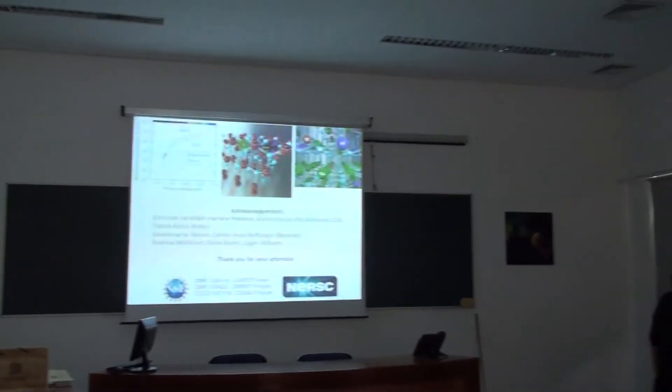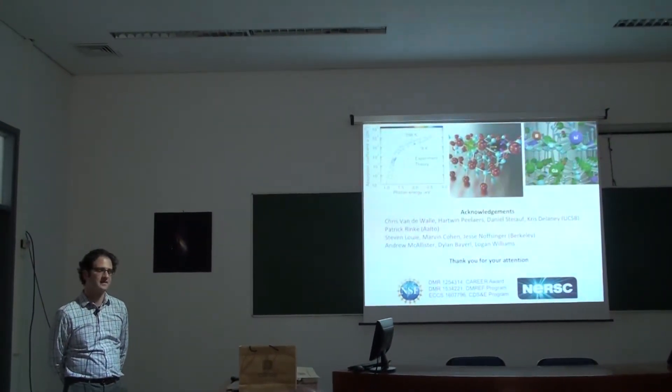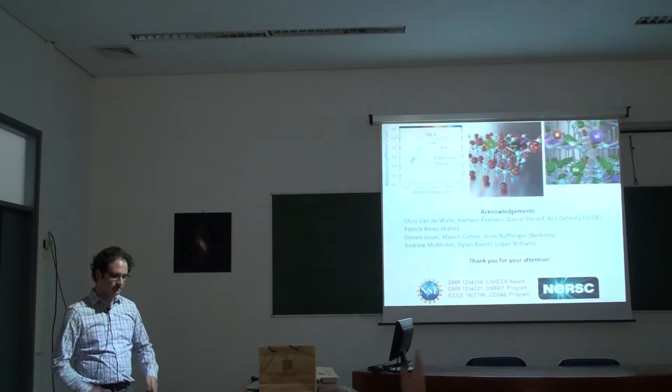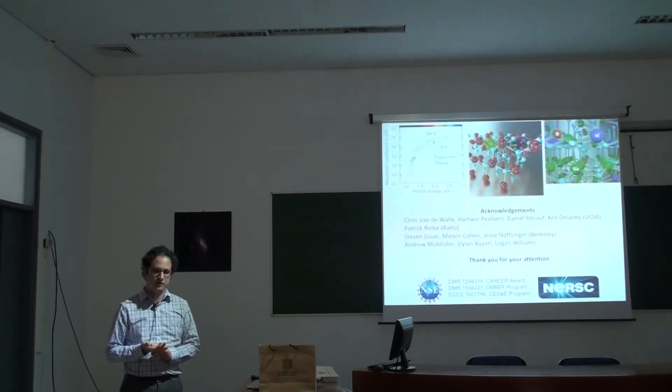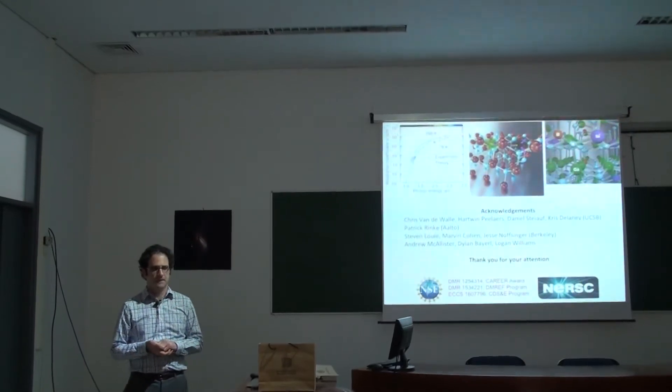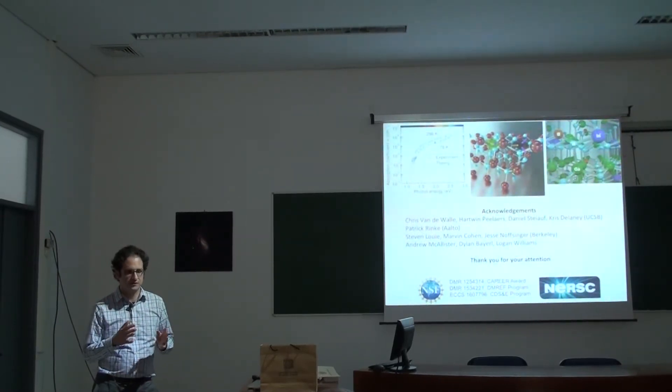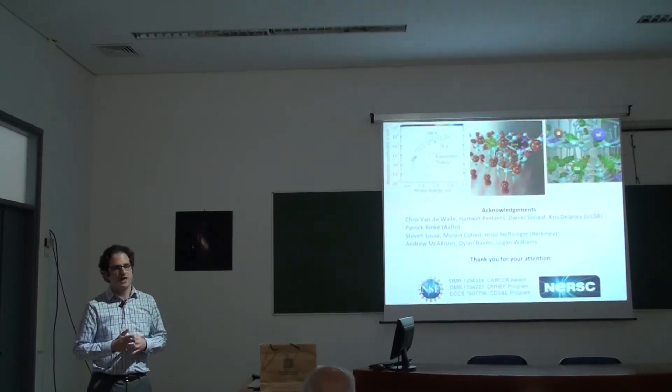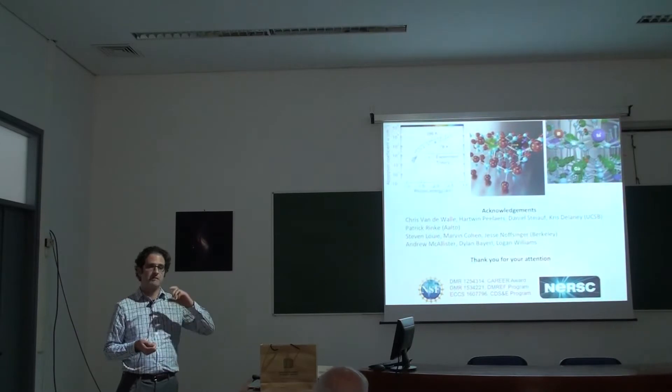Thank you very much. If you have questions? What is the form of the exchange-correlation functional you use, or is it different for different cases? Very good question. The question is about the exchange-correlation functional. I forgot to mention that in most cases we use the local density approximation, which is good for solids. Another one is the approximation by Perdew-Burke-Ernzerhof. They're equally good or equally bad for structural properties - they both give you about 1% difference in lattice constants. LDA underestimates, PBE overestimates. For solids it doesn't matter as much; for chemistry it matters a lot more to use more corrected functionals. The more important correction we make is to correct the band gaps with the GW method, because both functionals tend to underestimate band gaps. Sometimes we use hybrids - we use hybrid functionals that mix in some of the exact exchange, like hybrid functionals mixing some of the Hartree-Fock exact exchange. In that case if you use GW to correct the band gaps, yeah.